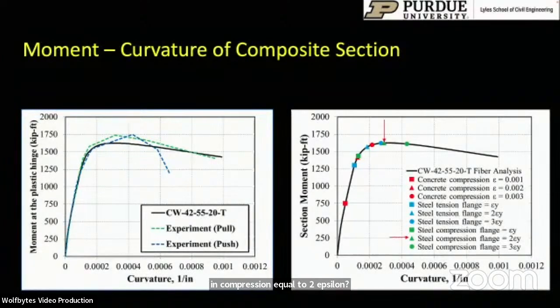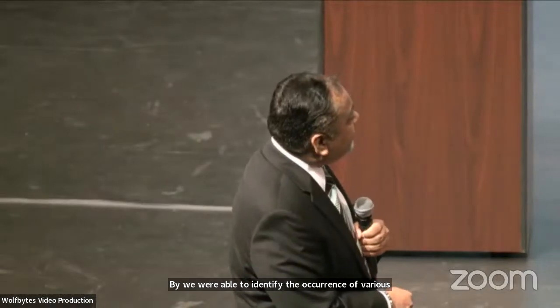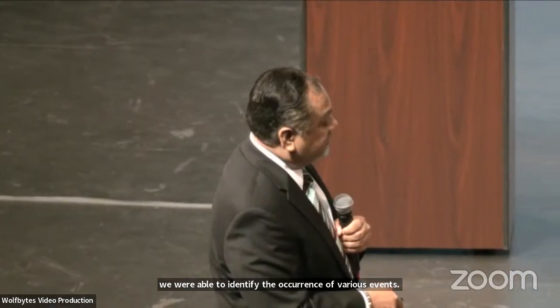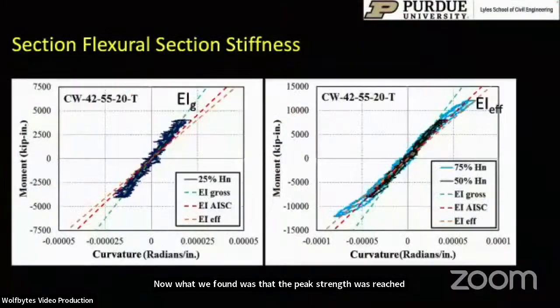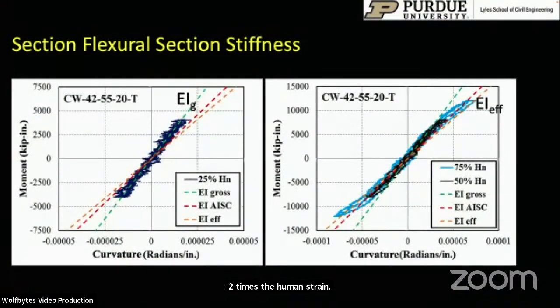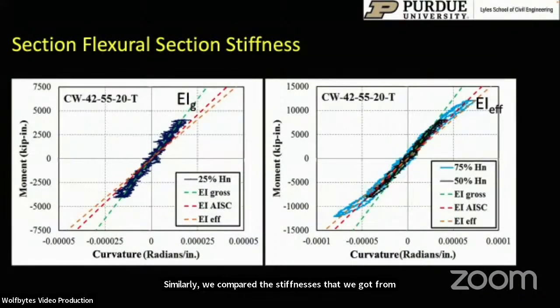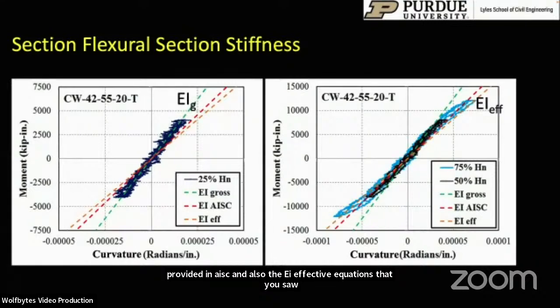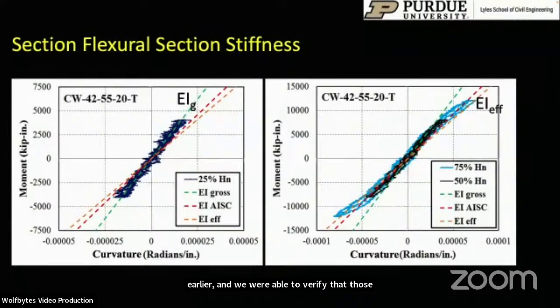And what we found was that the peak strength was reached when the steel in compression reached a strain of about 2 times the yield strain. We were able to learn this from the experimental data. Similarly, we compared the stiffnesses that we got from the experiments with the recommendations that we had provided in AISC and also the EI effective equations that you saw earlier.